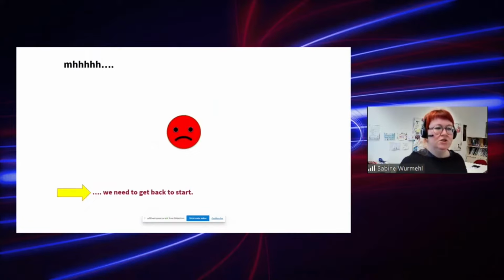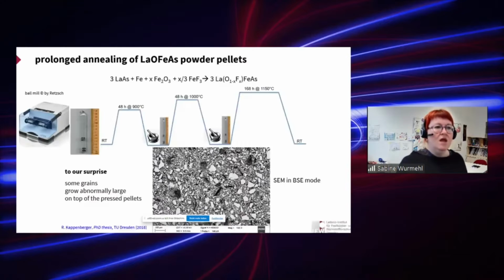So this is apparently an issue, and we need to go back to the start to tackle this problem. I had a very gifted PhD student, Rea Kappenberger, who was going back to the initial synthesis of polycrystalline materials of the 1111 compounds. She was mixing the precursors, lanthanum arsenide, iron and iron oxide, iron fluoride in the stoichiometric ratio, then using a ball mill to homogenize the material, pressing it into pellets, and doing a 3-step sintering process with intermediate grinding and repressing.